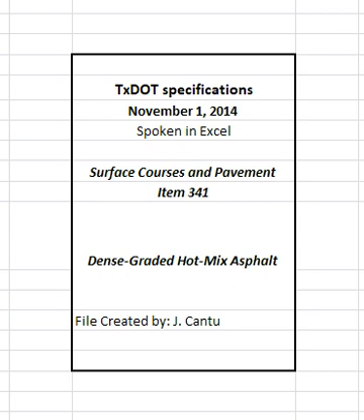Evaluate areas with severe thermal segregation by performing density profiles in accordance with Section 341.4.9.3.3.2, Segregation, Density Profile, DOT. Remove and replace the material in any areas that have both severe thermal segregation and a failing result for segregation, density profile, unless otherwise directed. The sublot in question may receive a production and placement payment adjustment greater than 1.000, if applicable, when the defective material is successfully removed and replaced.